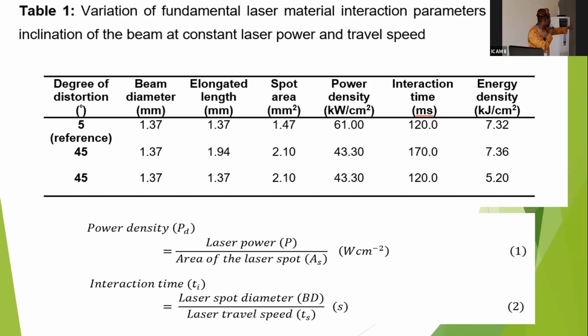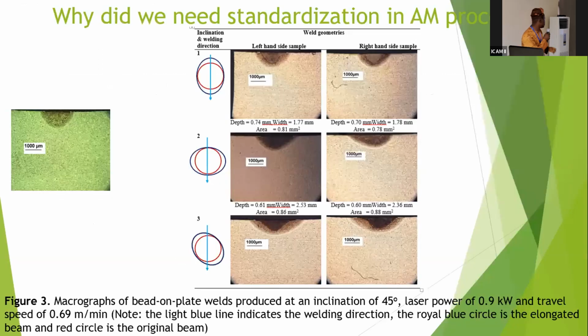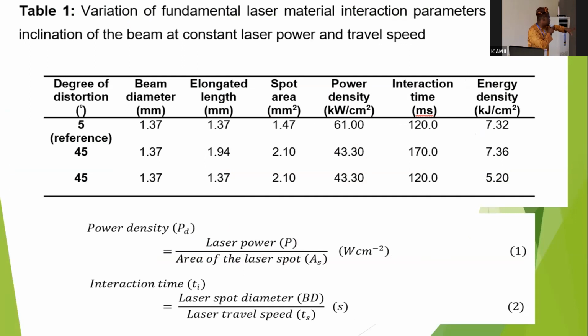So, meaning that if you are looking at the power density of the laser, which has a formula of laser power over the area of the spot, because the area of the spot has increased and you keep the same power, what is the power there? The laser power is 0.9 kilowatts, so the laser power that was used there is 900 watts. We use the same speed of 0.69 meters per minute. So when you are working at this rate, what it translates to in terms of energy going into the system is not the same.